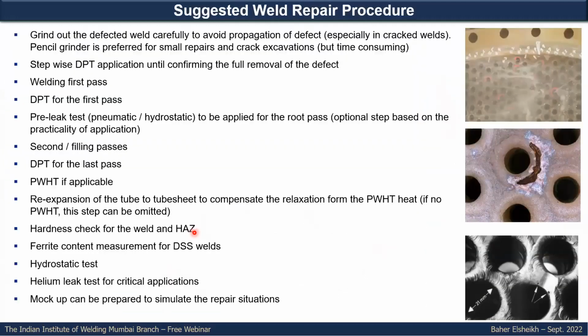Here this is a recommended or suggested procedure for the weld repair. First, you need to grind out the affected part, and this shall be done very carefully because especially in case you have some crack during the grind out, the crack might propagate. This is a risky application, so it's preferred to have a pencil grinder with careful application, although it is time consuming. Then apply stepwise DPT to confirm that the full